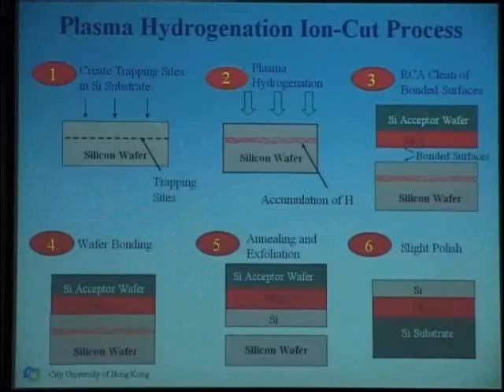So I'm going to talk about a new technology called hydrogen introduction by plasma hydrogenation. Previously, we implanted with some energy. But we can actually do another way by low energy hydrogenation. Instead of implanting, it's diffusion, diffusing hydrogen into the materials. And the way to do that is to create a defect layer right here by implantation first, and then have the hydrogen diffuse in. And after it diffuses in, you get bubbles. And the same idea, you bond with the wafer, and then you crack it. And then it works. So this is a much cheaper process.